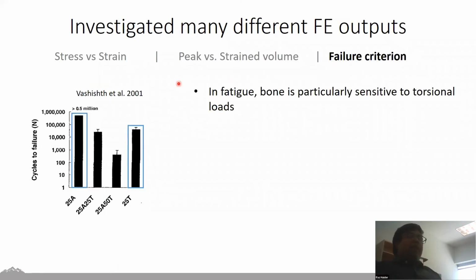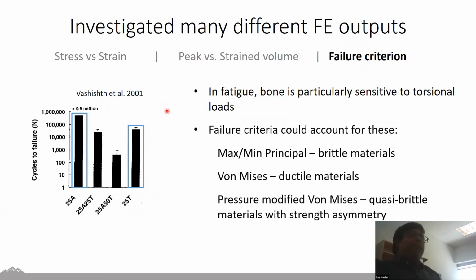The last thing that we wanted to explore in this study is this idea of failure criterion. And this was really motivated by that data by Vashishtha et al. that I was showing you guys earlier. Remember, when they did a load to 25% of the axial load versus 25% of the torsional load, their data seemed to suggest that bone was particularly sensitive to torsional failure, even when you account for the fact that there are relative differences in monotonic strength. So we thought that this is a phenomenon that we probably could incorporate into our models if we picked the appropriate failure criteria. And so in this study, we decided to explore 3 different failure criteria and see which one worked best. The first thing that we looked at was this idea of max versus minimum principal strain.